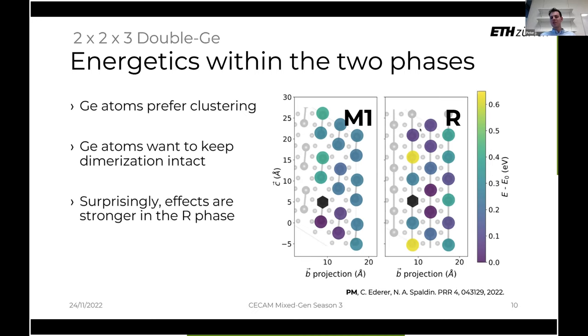Why? So indeed, I assume you mean exactly this cluster here. So for example, this configuration here, which in our labeling system we label GE03, in fact seems to want to keep the dimerization, because if we have a germanium atom here and another germanium atom here, this leaves two vanadiums in between, which then dimerize and then allow for the formation of this M1 phase. And of course, the way I'm describing it here is very simplistic, but I think it holds quite well if we remain in the same chain.